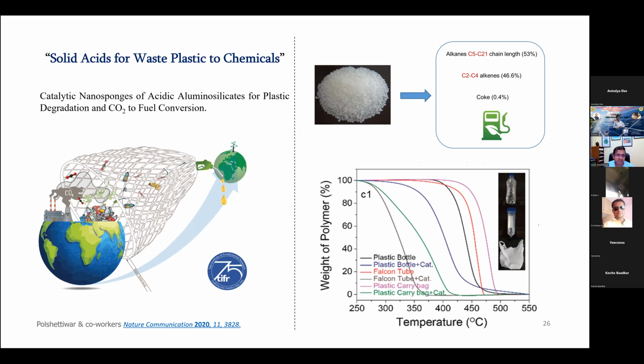The acidic strength of this material is very close to zeolite, which is known to be the strongest solid acid. But zeolite has micropores, and not all molecules can diffuse into micropores less than 2 nanometers, whereas ours has a wide pore size distribution up to 15, 20 nanometers, so even bigger molecules can diffuse in and you can do different catalysis.